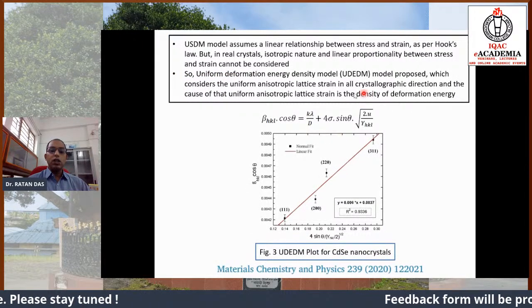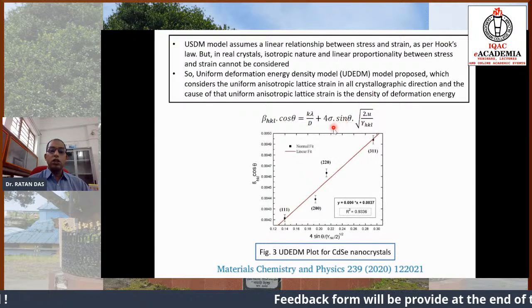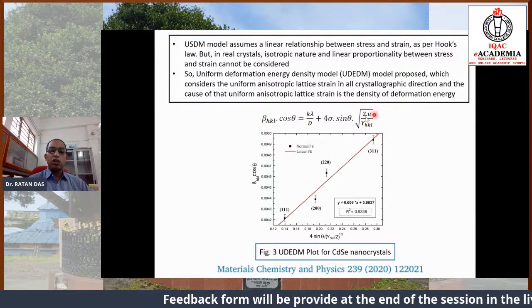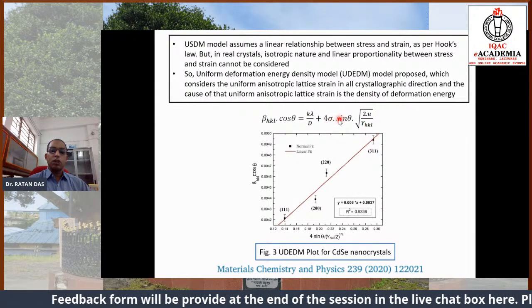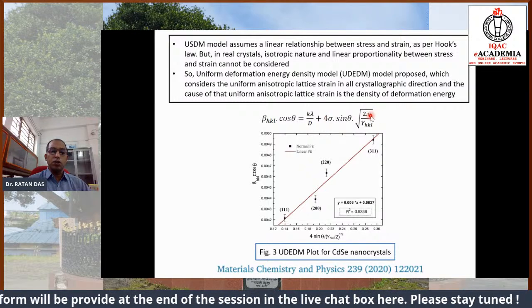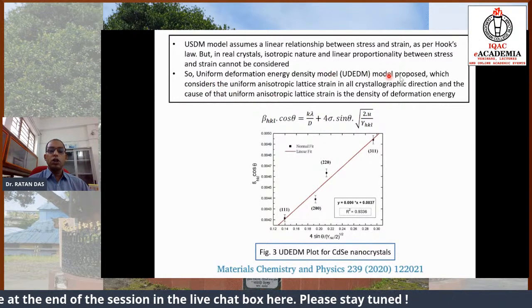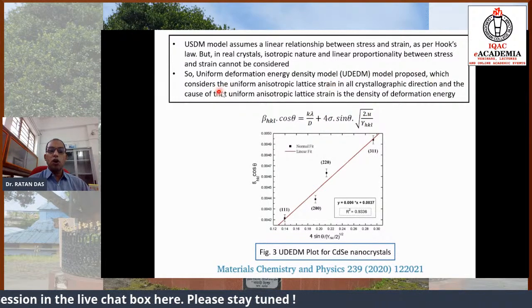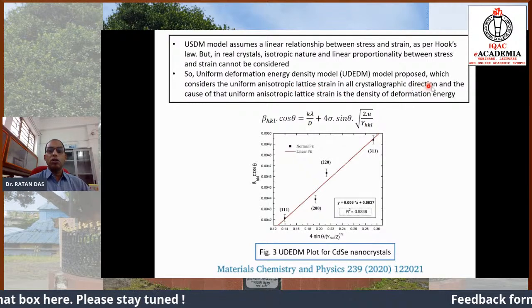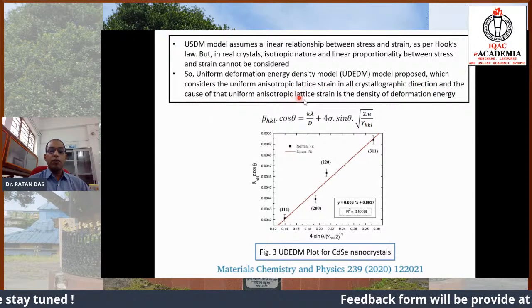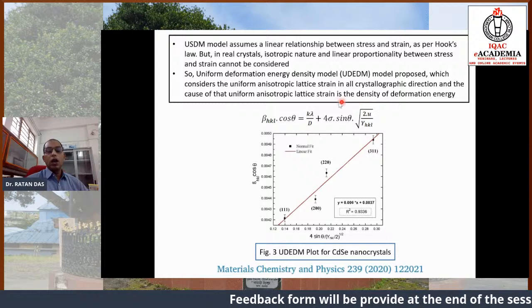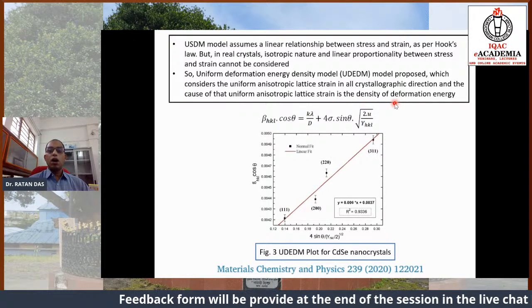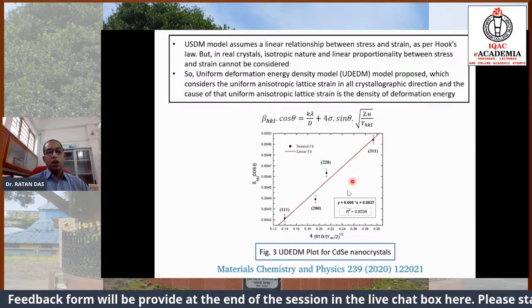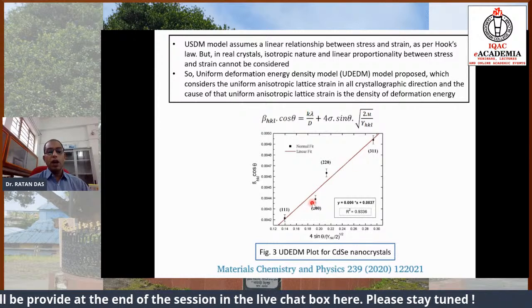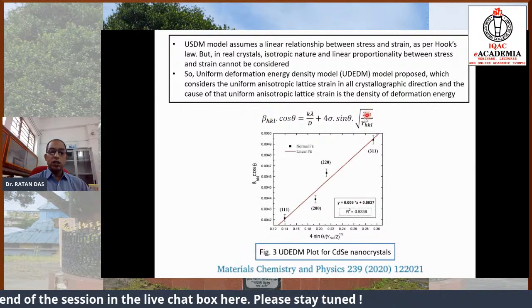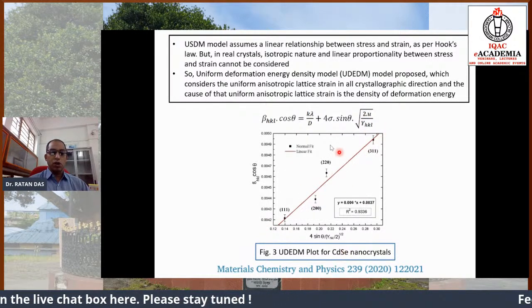Similarly, replacing with the energy in the system. Here the sigma is coming into the picture, but it should not be here. It is U. The energy deformation model considers the uniform anisotropic lattice strain in all crystallographic directions, and the uniform anisotropic lattice strain gives the density of deformation energy. In the same way, we can obtain the energy density by plotting.